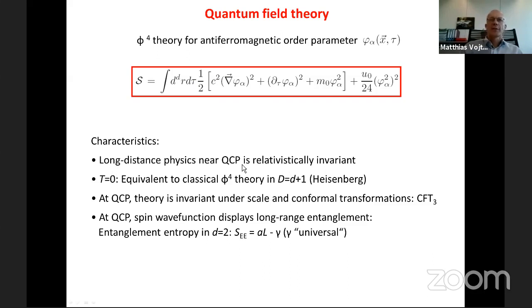And it has a number of characteristics which I've listed here. There is relativistic invariance, there's even conformal invariance. And there is actually, in a sense, long-range entanglement, which means that the area law, which I've advocated before, if you are, for instance, in 2 dimensions, the entanglement entropy is not strictly proportional to L, as it is dictated by the area law, but there is a correction, and this correction is universal. And this can be calculated within the conformal field theory and has been verified in numerical simulations.